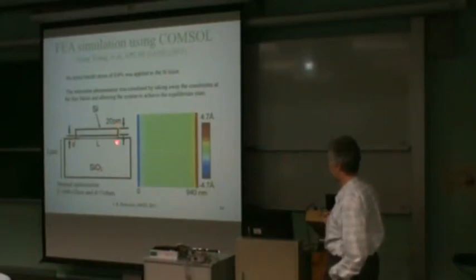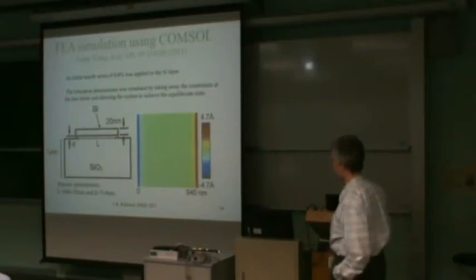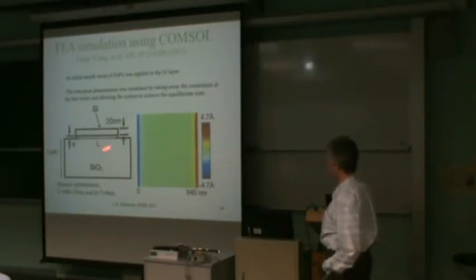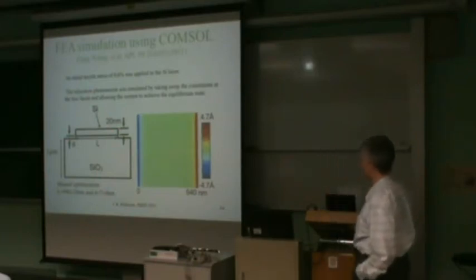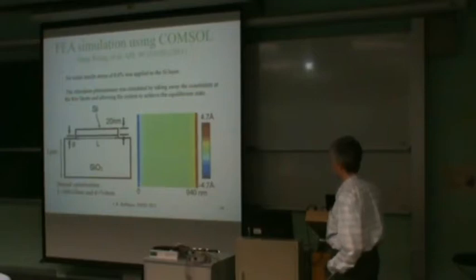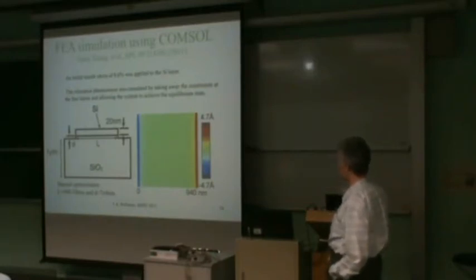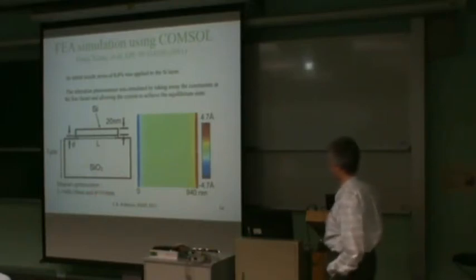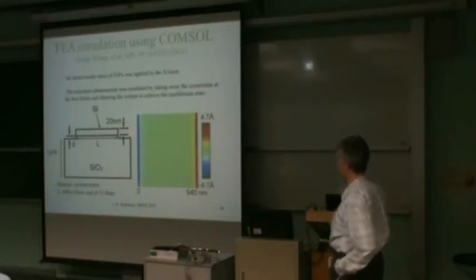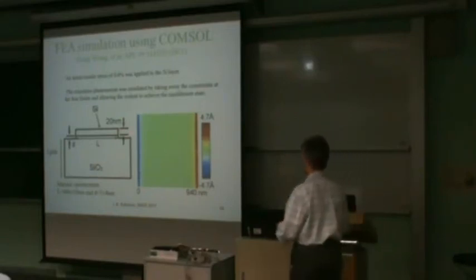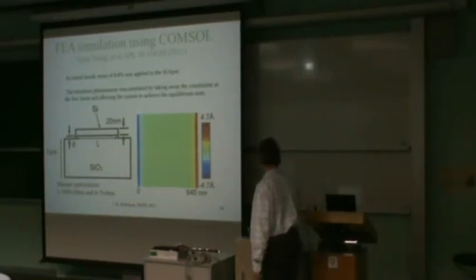And so if you build up a pedestal like this, which you could simulate relatively easily, then you could get a good fit to the curve I showed before. It's a fit from the COMSOL. Actually, I don't remember if that was just an exponential or the result from the COMSOL, but we get good agreement with the simulation with an overcutting of about 7 nanometers that was determined here. So we've got good agreement with classical elasticity for the relaxation of this thin layer.